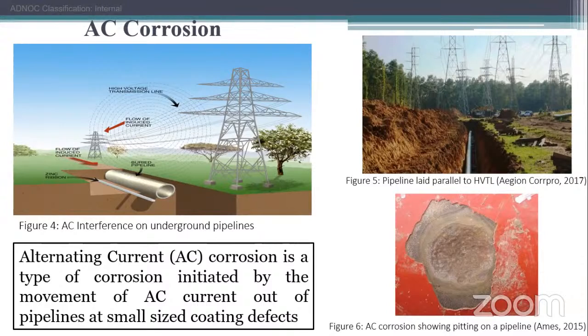So at the point where it's leaving the pipeline, it causes the corrosion, like what we can see in figure 6. You can see an indication like this in figure 6, at the point where it's leaving the pipeline, like a pitting. So when you see these pictures, you can imagine that this may be due to alternating current effect.